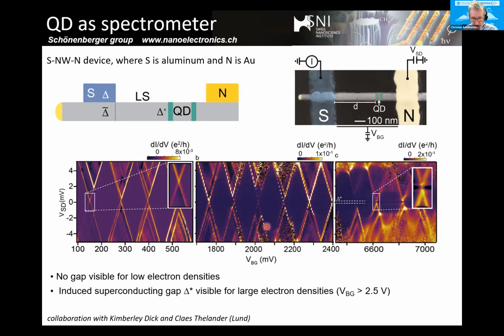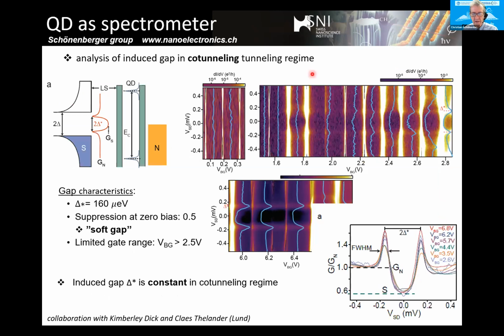And what we do next, we're going to look in the co-tunneling regime. This is shown here, so this is now a zoom in. This is a scale of 500 micro eV. We look at the function of gate voltage again, and the blue line is a spectrum taken in the middle of the Coulomb blockade diamond, so this is the co-tunneling regime. You just see noise here at low bias, low gate voltage. If you go to larger gate voltage, then at some point there is some feature appearing, right? Some kind of a gap.